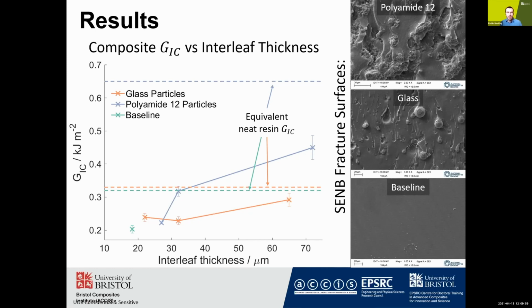The glass particle interleaves are much closer to reaching the equivalent resin value, indicating that at 67 microns here, that's close to a fully developed plastic zone for this material. However, there's a much bigger difference between the polyamide particle interleaf values and the equivalent resin at comparable thicknesses. This indicates that the ductile particles promote the formation of a larger plastic zone.